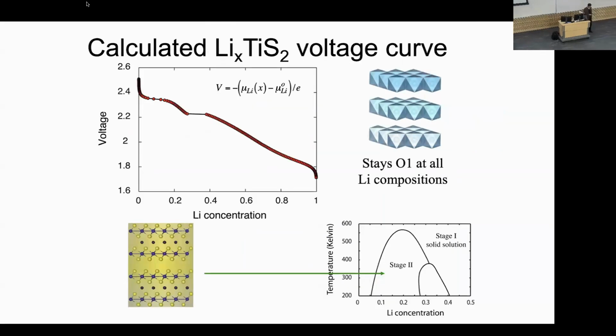Well, if we insert lithium in this layered material, TiS2, we'll take TiS2 as the model system. This is the voltage curve that we get, very smooth. Smooth voltage curves mean just disorder. Here, there's a little plateau, which means a two-phase region, and a little step, which means it's staging. So it wants to have filled layers, empty layers, filled layers. That happens over here. But other than that, not much is happening.